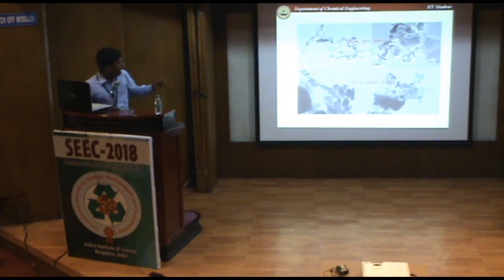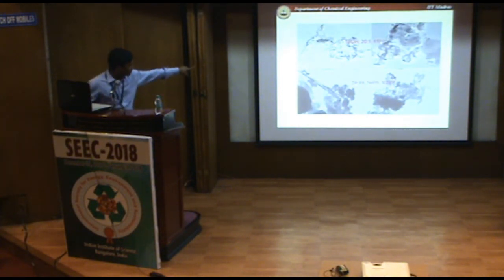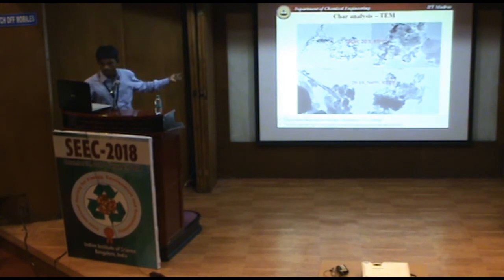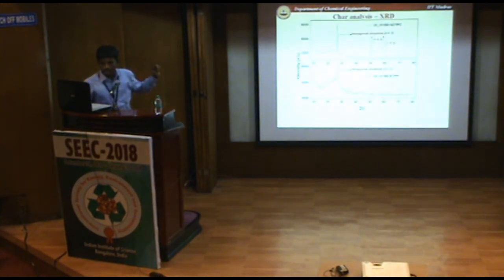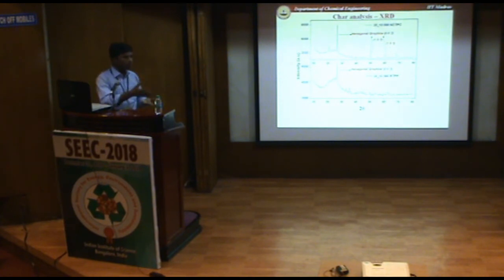This is SEM and TEM. In TEM also you can see carbon structures. This is 50 nanometer and this is 100 nanometer. So carbon tubes and carbon spheres and other small particles in this TEM. And XRD shows the formation of the hexagonal graphite is more in the char part actually. That is the 002 layer. That means if you take the XYZ plane, only one plane has grown sheets, a lot of graphite sheets have formed on the surface.